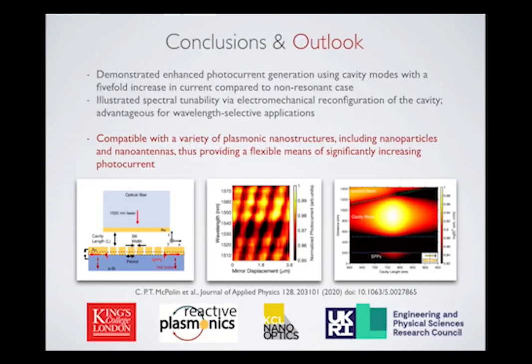In summary, we have successfully performed a proof of principle experiment illustrating the cavity-enhanced and wavelength tunable photocurrent provided by a cavity-based architecture. The device exploits cavity-driven plasmonic modes to greatly improve the performance of sub-bandgap photodetectors. A 5-fold increase in the photocurrent was recorded compared to the non-resonant case, illustrating the potential of this approach, which can be adapted to include other plasmonic structures. We have also demonstrated dynamic reconfiguration with respect to the operating wavelength, thereby expanding the functionality and paving the way for future tunable photodetectors. Thanks for your attention.